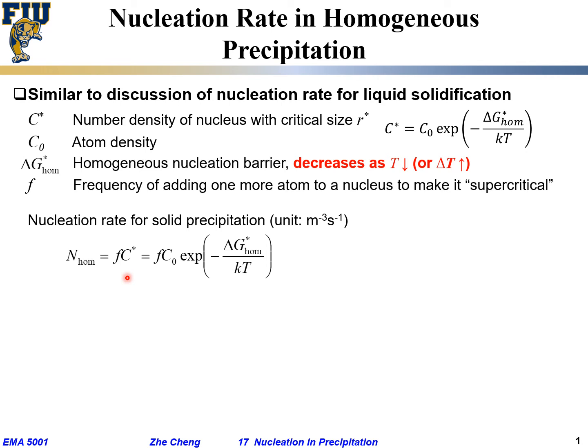We depend on two things: what's the number density of these so-called critical nucleus, and how frequent we are adding atoms to it. If you are not adding atoms to it, the nucleation rate stays zero, right? Because even if it forms, it doesn't grow. On the other hand, if you are trying to add but your number density is too low, your nucleation rate is low. So that's this factor, and then we put the C* from here—the C* we write it as C0 times this exponential term.